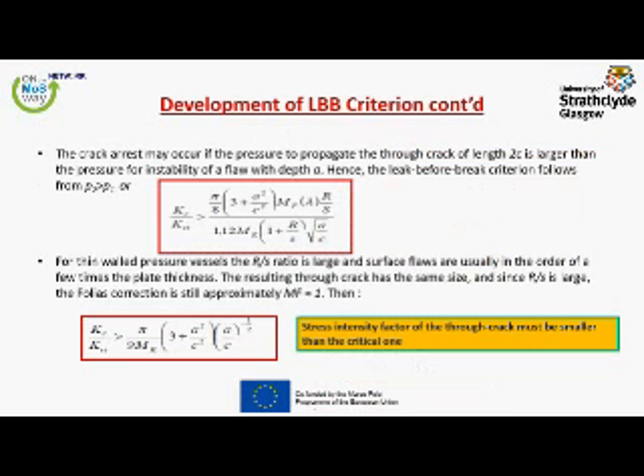So eventually, we end up with this formula, which will give us a condition which, if satisfied, we are not going to have critical crack propagation. What we are going to see, the crack will go through the thickness, we are going to see leak. We know when we have leak. How do we know? We know because we are going to have gas detectors in the interbarrier space. Interbarrier space is the space between primary and secondary barriers. So the detectors will go off. We know that something is going on. So the leakage, which has to be contained for 15 days, will be known. So we can take care of it. The problem that we know is easier to tackle than the problem we don't know.